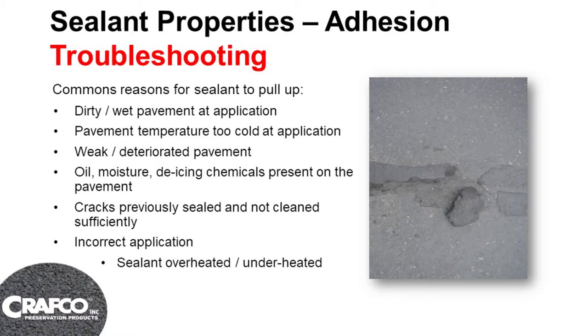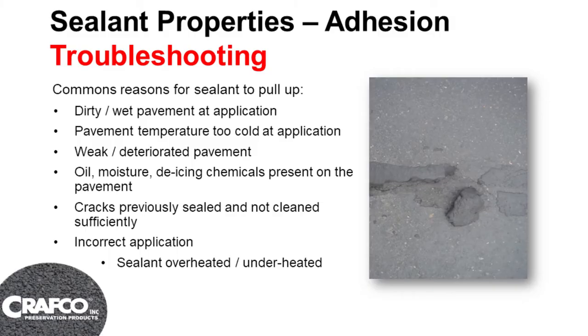Some of the problems with adhesion — if there were a Ten Commandments of Crack Sealing, the first two commandments would be clean and dry. Crack sealant will not stick to moisture, it will not stick to dirty pavement. It will stick to the dirt just fine, but it's going to adhere itself to the first thing it comes in contact with. Also, you've got weak and deteriorated pavement where the surface is oxidized and you just don't have a good surface to bond to. And cracks that were previously sealed — the new crack sealant is only going to stick to what it comes in contact with, and if that's old sealant, it's not necessarily the best scenario for a new job.